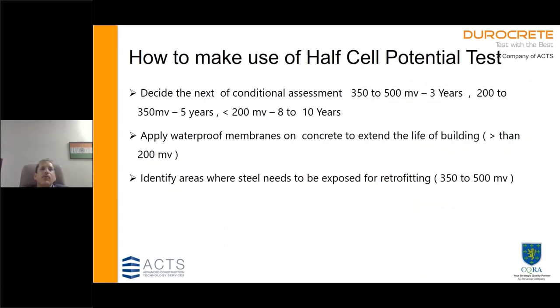So generally, how do you make use of half cell potential to take decisions? If the half cell potential is between 350 to 500 millivolts, you need to do frequent condition assessment of the building. So the next inspection due will be very frequent, maybe 3 years. If it is between 200 to 350 millivolts, you may do it after 5 years. And if the potential difference is less than 200 millivolts, you can take a longer term for the next inspection.